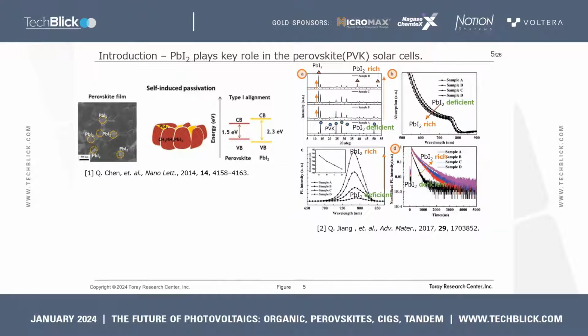Now here's the main issue. In perovskite solar cells, PbI2 formed on the surface plays an important role. The reason for this is that PbI2 has a larger band gap than perovskite and thus acts as a passivation layer. This is demonstrated in the measurement examples on the right.